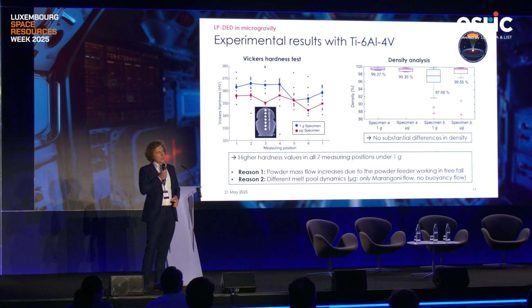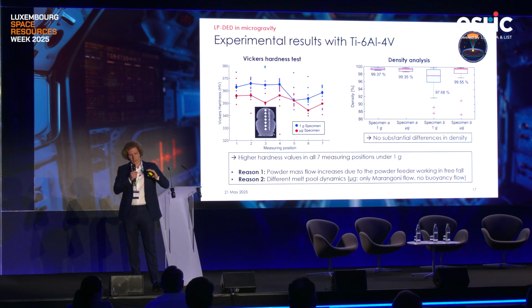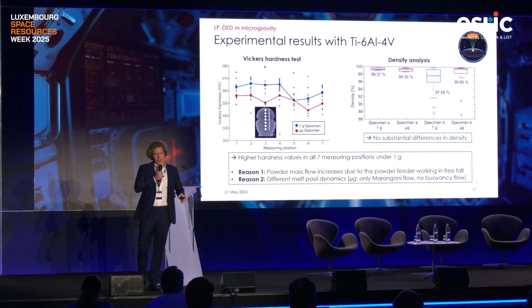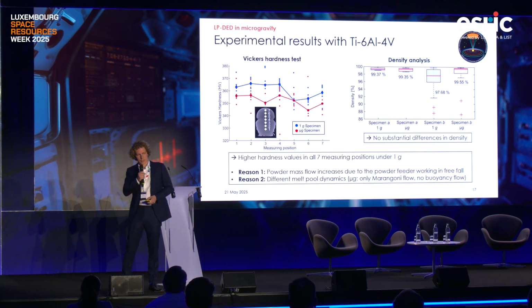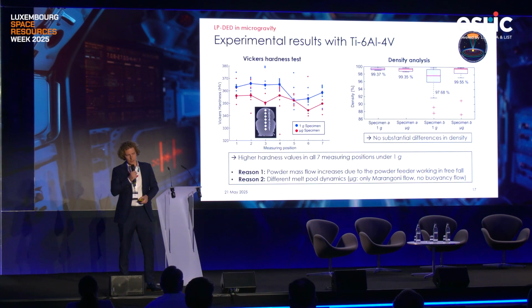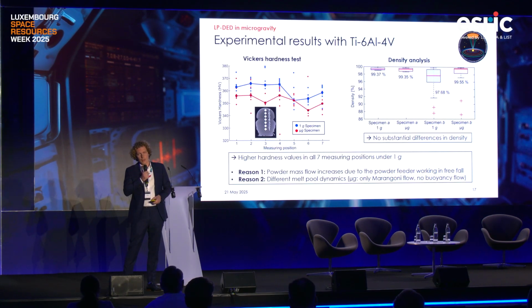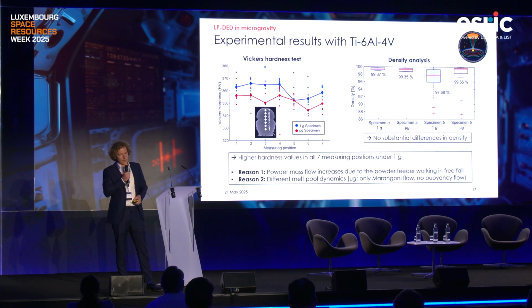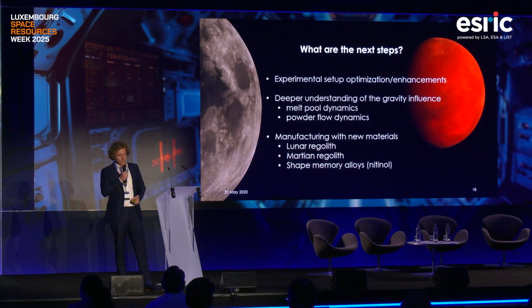Therefore, we have 2 reasons. First one is that the powder flow mass increases due to the powder feeder working in free fall. So there we have a little bit, the volume of the specimen is a little bit higher. We're working on that, but it could be, reason 2, that there are different melt pool dynamics, because in microgravity there's only the Marangoni flow and no buoyancy flow.